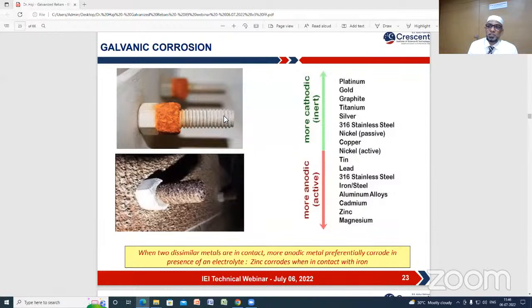So this logic is what is used in the galvanization process. If you apply zinc coating over the steel, in the electrochemical series we can see that zinc is beneath iron and steel. So if we apply a zinc coating over the steel, zinc will sacrifice itself, protecting the steel. In this photo, you can see the nut is a noble material and the bolt is a less noble material. If we apply zinc coating, zinc is the less noble material compared to the steel. So whenever corrosion conditions happen, the zinc slowly sacrifices itself so that the main metal does not get affected. Some of you may ask how long it will protect. Depending upon the thickness of the coating, we can design the structure for its service life.